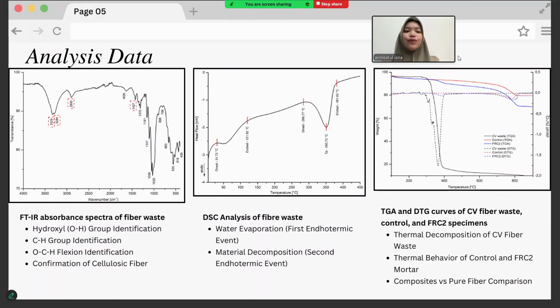degrees Celsius. The TGA curve shows that viscose fiber decomposes completely between 330 to 390 degrees Celsius, typical for cellulose. In contrast, the control and FRC2 composite saw smaller weight losses, about 10 up to 20%, indicating that the fibers interact with the cement matrix and alter its thermal behavior. Together, this analysis confirmed that viscose rayon fiber can withstand moderate thermal conditions and remain stable within the cementitious composite. Next,